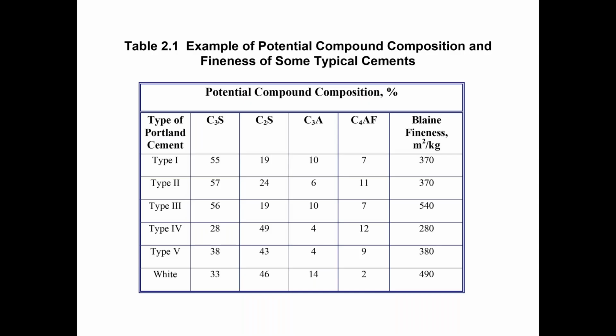Right, look at type 3. Notice that the compound composition of type 3 is very similar to the composition of type 1. It's basically the same. A little bit of variation in the C3S, but other than that, it's basically the same. The big difference between type 1 and type 3 is that Blaine fineness. So essentially a type 3 cement is a type 1 cement that is ground more finely. We already learned from chapter 1 that the finer a material is, the more surface area it has. So when it comes to chemical reactions, generally the more surface area one of your reactants has, the more quickly that reaction is going to take place. And so that's exactly what we see here with type 3 cement. It's ground more finely than the type 1.